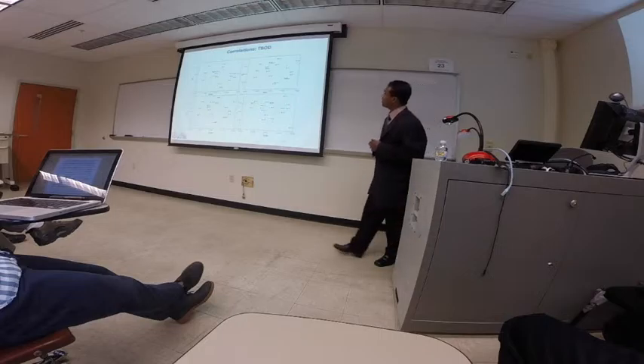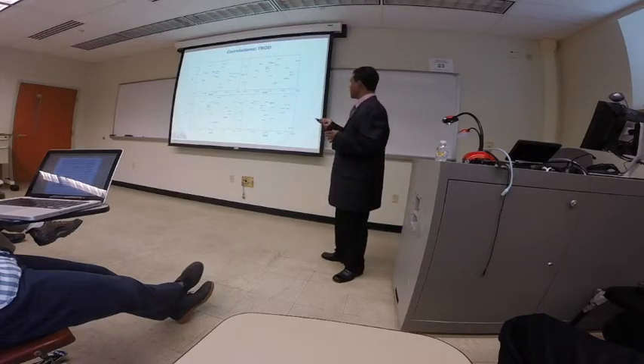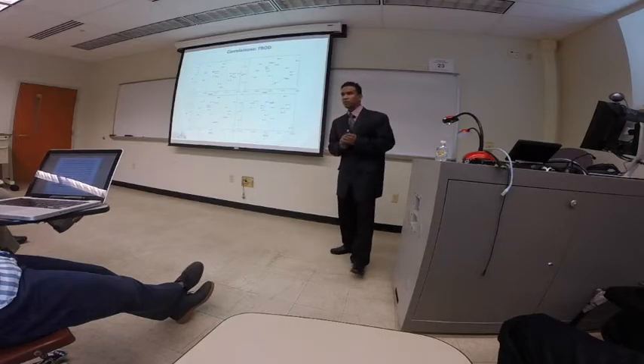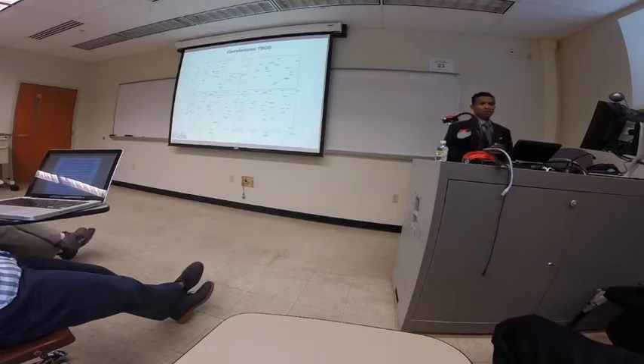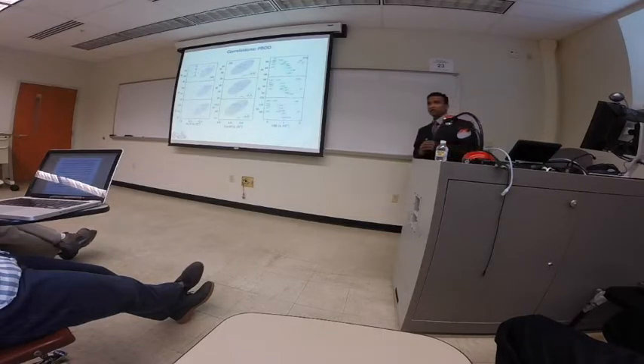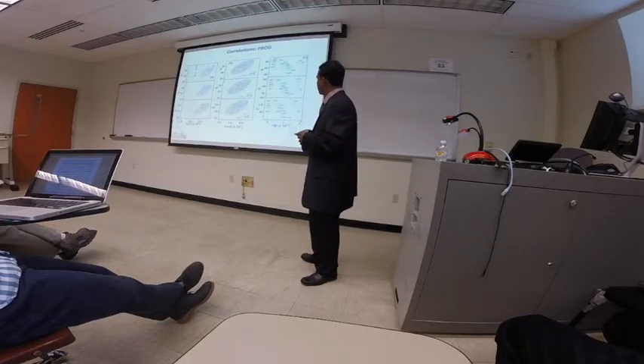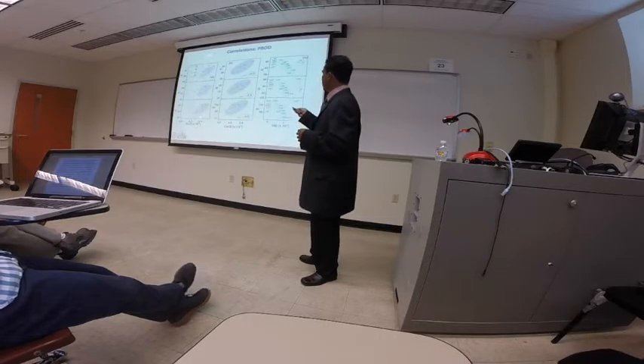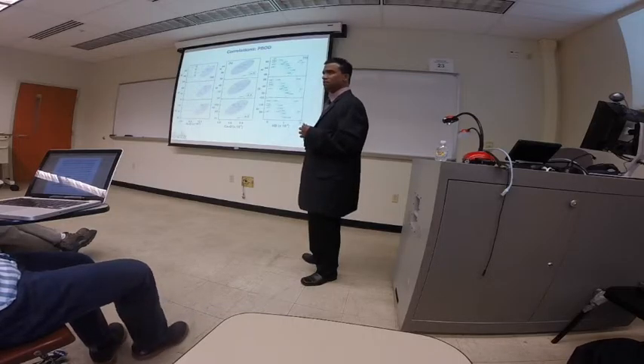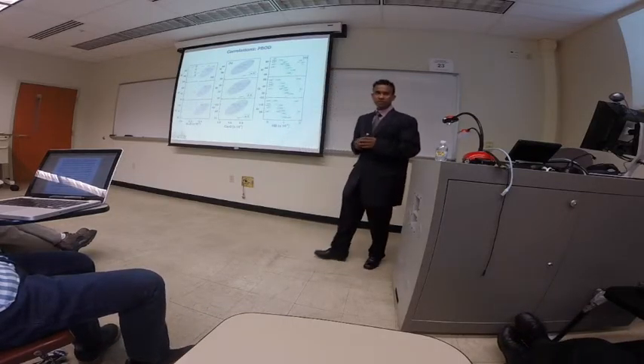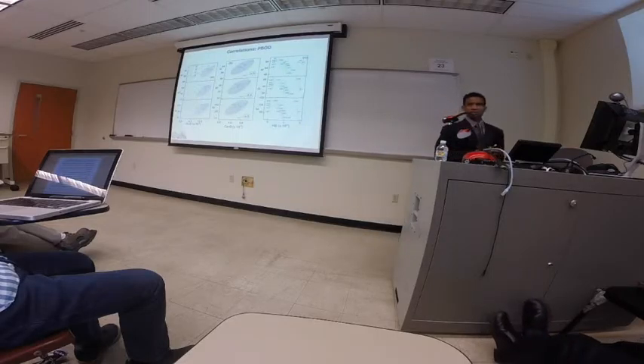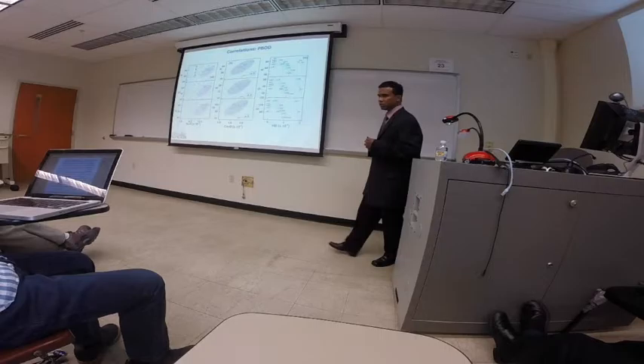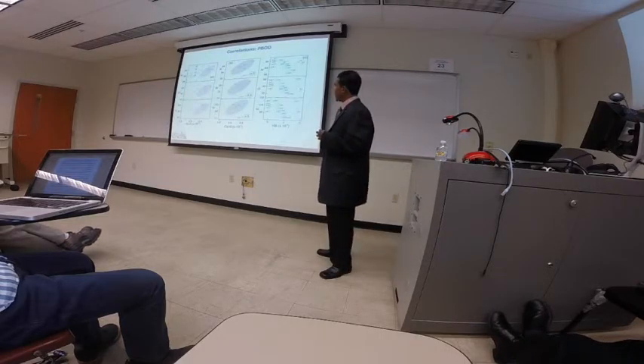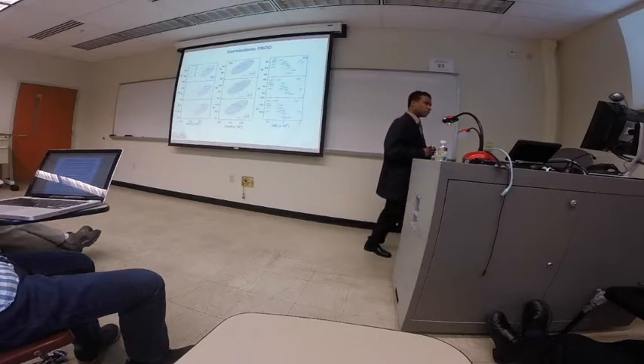Then we tested our TBOD metric against mechanical properties, and unfortunately we found that TBOD by itself does not correlate at all with the bulk mechanical properties. So we went further and analyzed the partial bond order density, PBOD, for each species: silicon oxide, calcium oxide, and hydrogen bonding. And you can see that, going against the norm, silicon oxide bond order density gives the least correlation with the mechanical property. It is widely accepted that silicates will govern the mechanical properties of cement, but that does not seem to be the case if you consider the electronic structure.